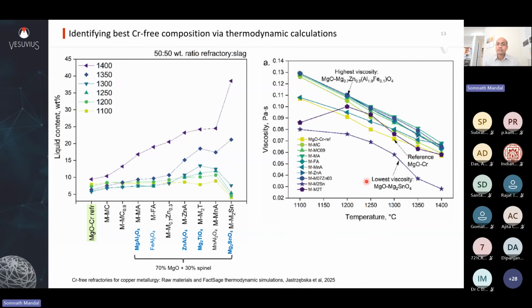Very good questions. The viscosity plot that I showed you is from FactSage thermodynamic calculations. It gives you predictive values of a desired refractory with slag mixture. Let me break it down a little bit for you. What you see here is magnesium stannate 30% with 70% magnesia. So that's your refractory. Now this refractory is mixed 50% with slag, so you have 50% refractory, 50% slag. Whatever composition you get, you put in the FactSage software, and you put temperatures 1400, 1350, and so on, and at each temperature it gives you the composition, how much liquid you are forming, and how much solid solution you are forming.